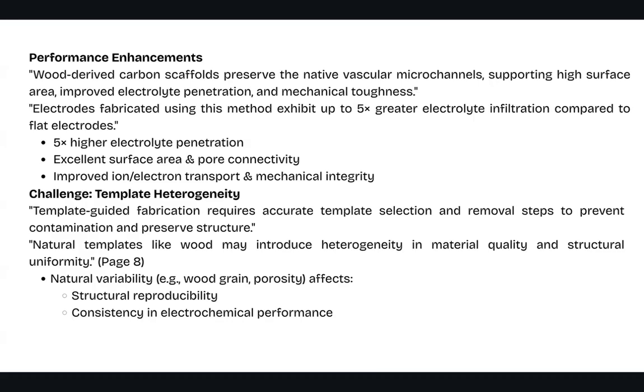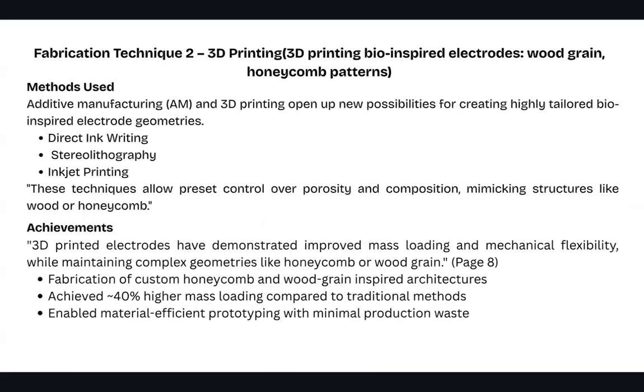So what is the challenge? The challenge is template heterogeneity. Template-guided fabrication requires accurate template selection and removal steps to prevent contamination and preserve structure. Natural templates like wood or coral may introduce heterogeneity in the material quality and structural uniformity. So what we can see here is there's natural variability, for example, the wood grain or porosity. So what does this affect? This affects the structural reproducibility and the consistency in the electrochemical performance.